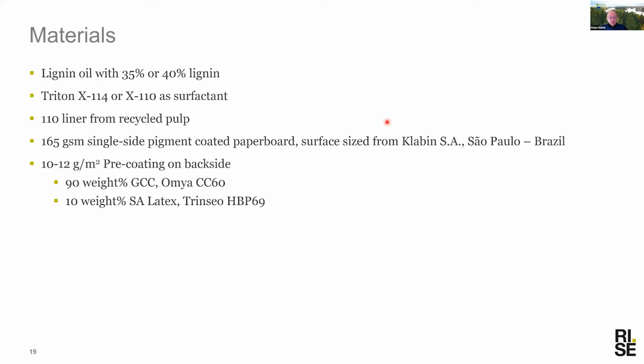We actually put together a lignin oil with a modified lignin and vegetable oil with different lignin contents, 35 to 40%. Then we used a surfactant that would place itself in the interface between the oil phase and the water phase. So what you basically do is stir around the whole system with oil and water, and you end up with something that looks like one phase, but it's not. So it's a little bit like making a salad dressing in lignin oil, and then we put the surfactant to stabilize it.